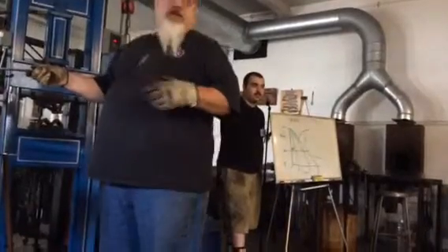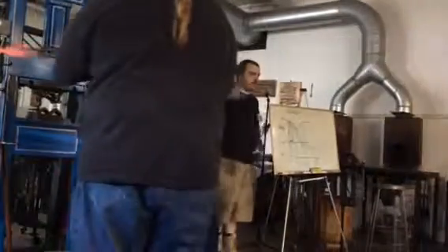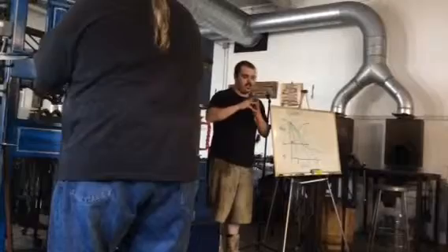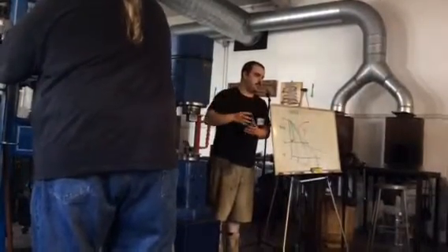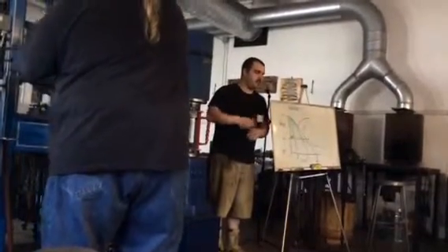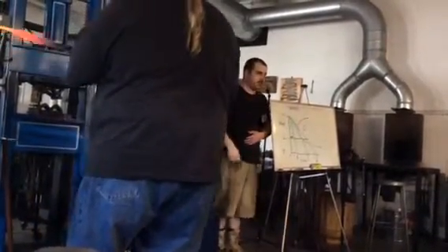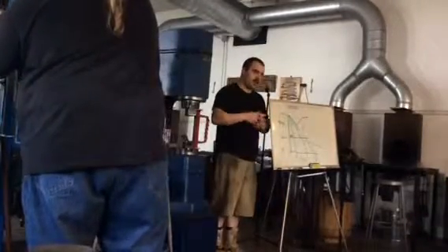And then imagine this room filled with sand and how hard it would be to get through the room. Because when those grains are large, they're more apt to break away from the structure. So if you look at the edge under a microscope, you'll see these large grains, and you try to put a fine edge on there. And of course, the grains being large, they're brittle, they'll pop out, and they'll take a huge chunk of that edge with them. The grains are fine.